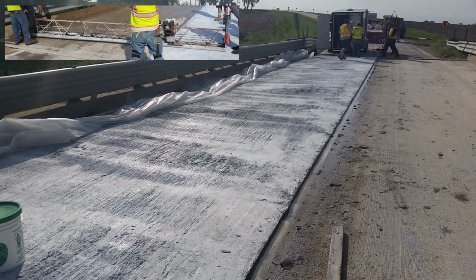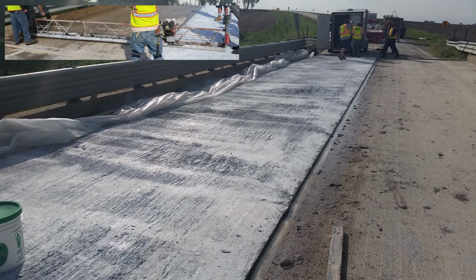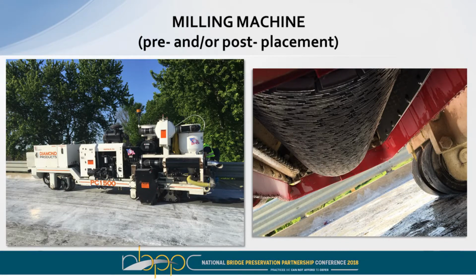So this is the first job. You can see the finish on this was not great. The contractor that did this, we kind of rushed through this job, unfortunately, and they used a screed that had a very low vibration input. And so the screed wasn't really consolidating the material as it passed over. It was kind of dragging the material, and we ended up with a very, very rough finish. What we've seen on subsequent jobs is if you have a screed with enough vibration, you get a pretty clean, kind of stricken surface. But nevertheless, on a lot of these jobs, they come through and they do a post milling process anyways, using a milling machine, which either you're using before to prep the deck or after to kind of finish off the deck.